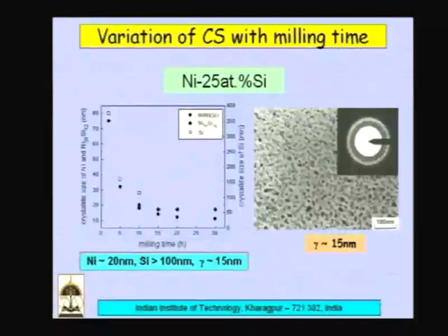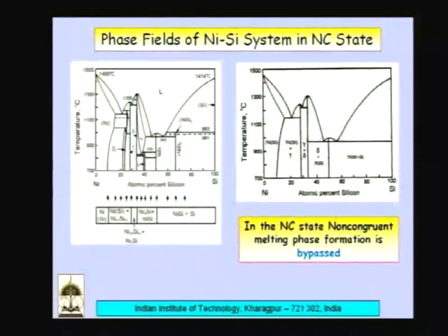If you look at that particular composition of about 25%, which phase is more stable? That is the phase which forms by such a reaction. But what is crucial to understand is that this always happens only in a nanocrystalline state. So, making nanocrystals is crucial for such compounds.